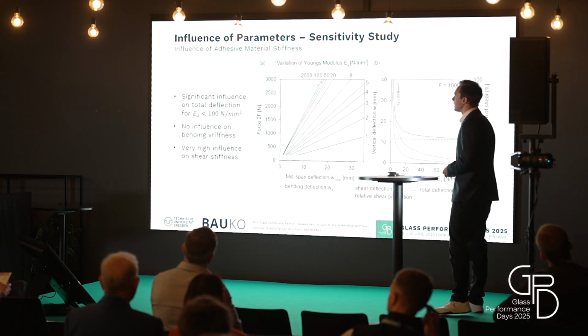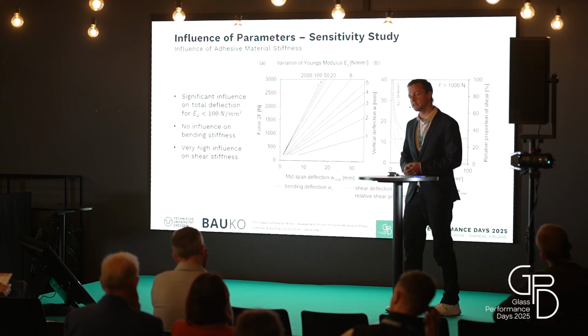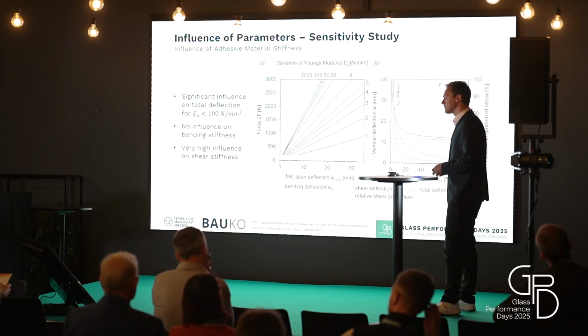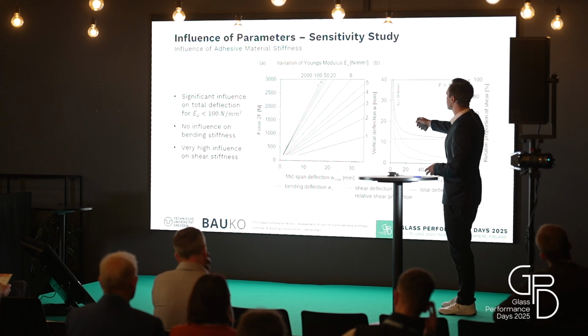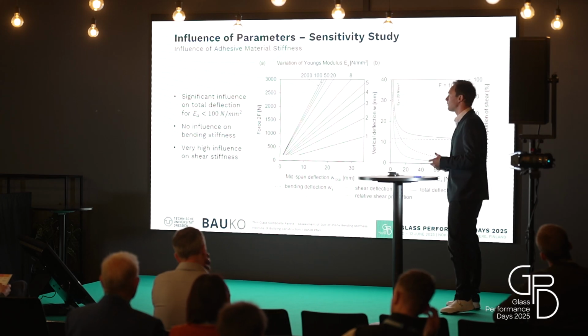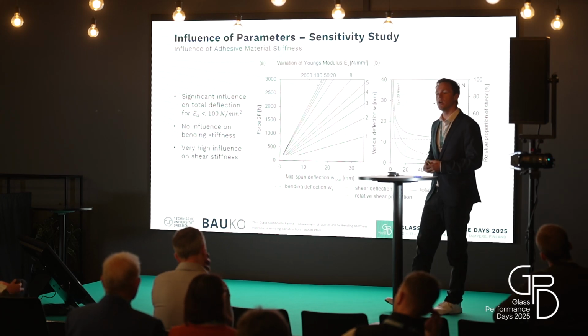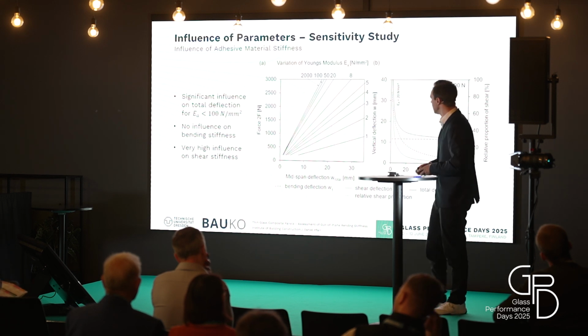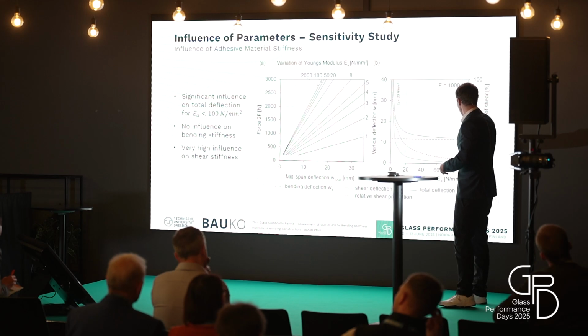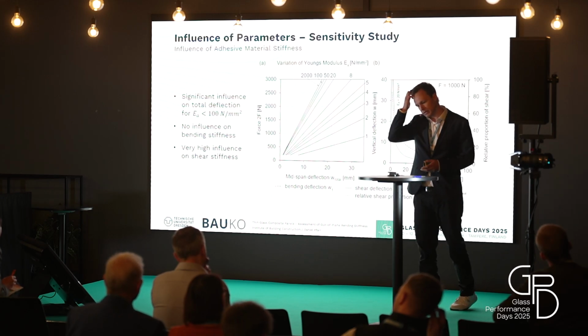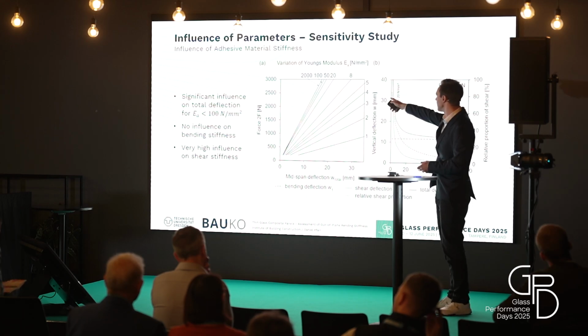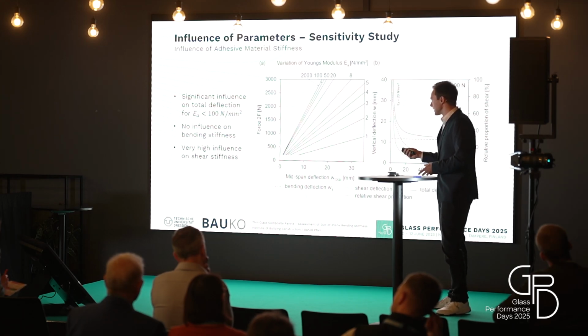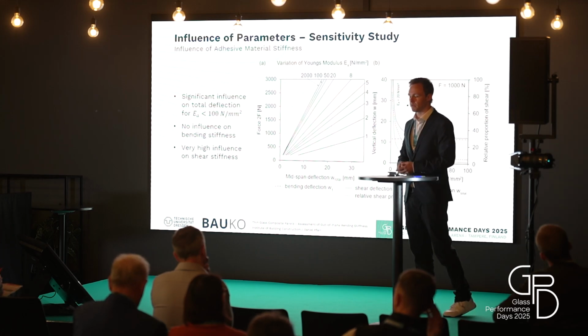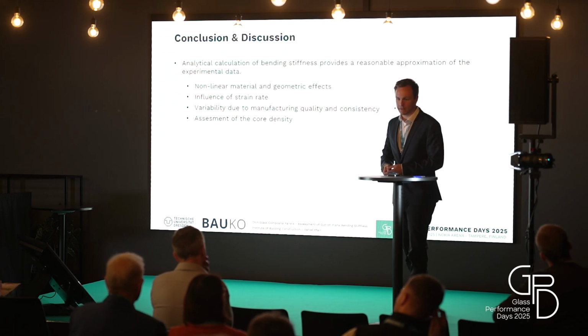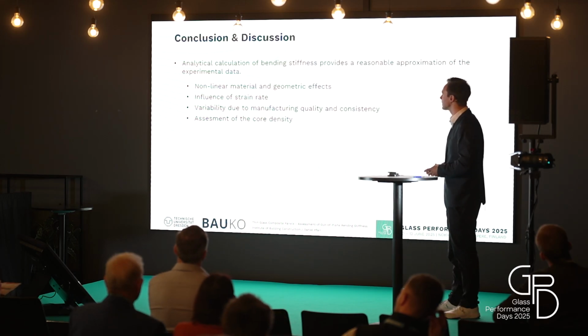The fourth and last parameter we have investigated is the adhesive material stiffness. We said, okay, we have an adhesive which deforms quite a lot. So we have varied the Young's modulus between 1 and 2,000 Newton per square millimeter. And in that case, it was also quite interesting that we have a very significant influence on the total deflection when we have a stiffness below 100 Newton per square millimeter. And as soon as we keep this threshold above 100 Newton per square millimeter, then the deflection is not increasing that much, which we can see already here on the left-hand side of the picture. In that case, we have no influence on the bending stiffness, but a very high influence on the shear stiffness. So, to come to an end and have a short conclusion and summary.